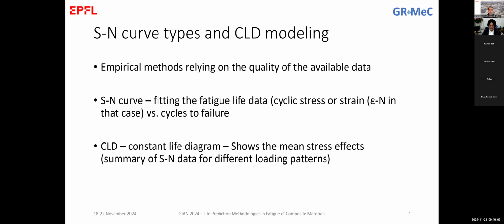all of them. So actually, as we said before, S-N curves and CLDs are empirical methods that rely on experimental data. We get the data and we fit the data, and if we fit the data, we have a curve. It's obvious. And then we call it the S-N curve when we fit stress-life data. We also have similar curves when we plot strain versus cycles on what we call the epsilon-N plot. By the way, strain-life plots are very common in the cases where we care a lot about low cycle fatigue. And these epsilon-N curves are also common in metals.